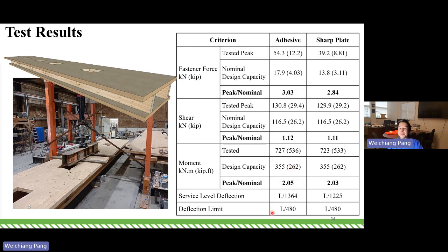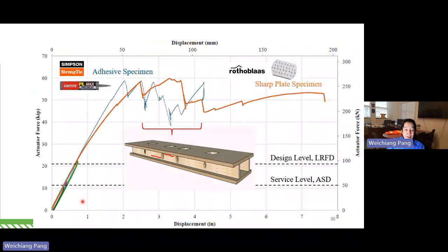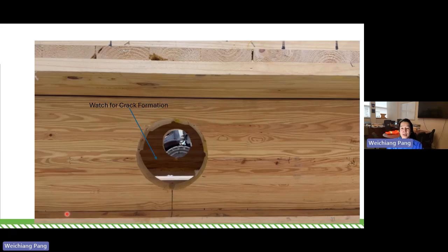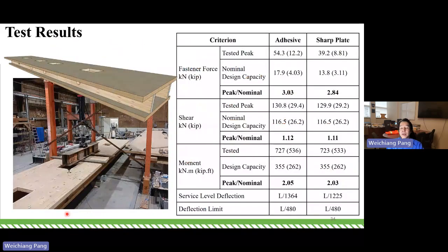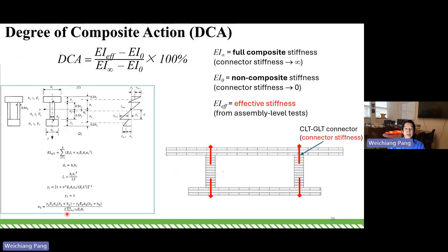For deflection, we target L over 480. Actually, this floor system is quite stiff here. The deflection at the service level is not an issue. By the way, service level, well, let me come back here. That's the deflection at this level, the service level. So we targeted L over 480. In fact, we get something very low here. It's actually L over more than 1,000. There's no issue. So the conclusion here is strength is not an issue. Even deflection is not an issue, right?